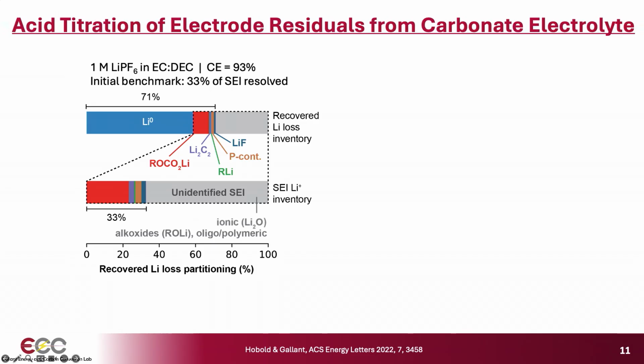So we looked at, as an initial demonstration now a couple of years ago, quantifying the capacity loss breakdown in this conventional carbonate electrolyte, 1 molar LiPF6 in EC-DEC, and we were able to assign about 70% of the capacity loss at that time. So you'll notice in this particular case, most of the capacity loss went to forming lithium zero or dead lithium, and we could resolve of the SEI losses about a third of them, with the majority of them going to these CO2 evolving phases such as lithium carbonate or semicarbonate. But obviously there was quite a shortfall here, and this is really corresponding to the phases that were not reactive with acid, so we didn't have a way to detect what was there.